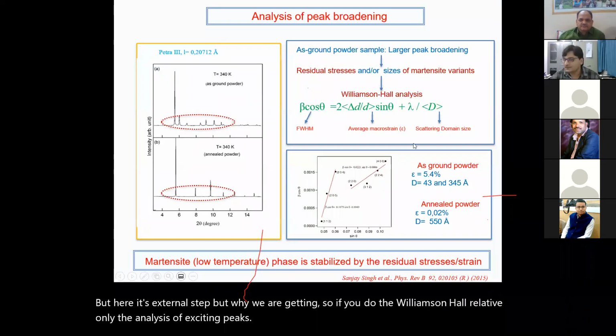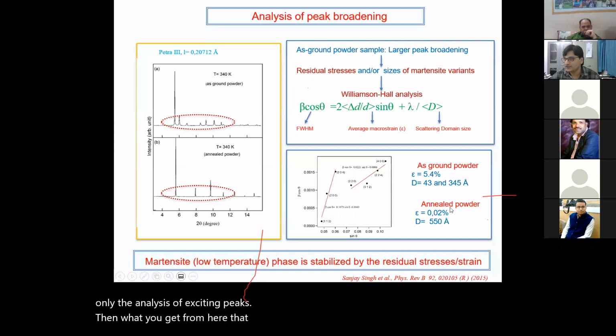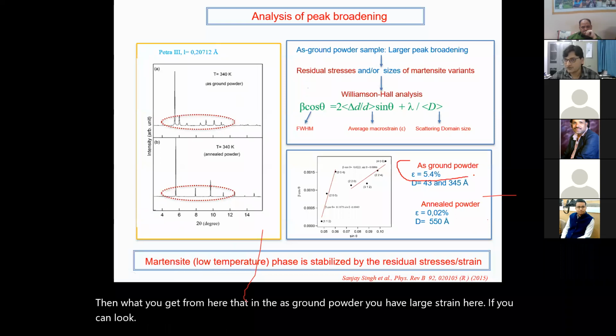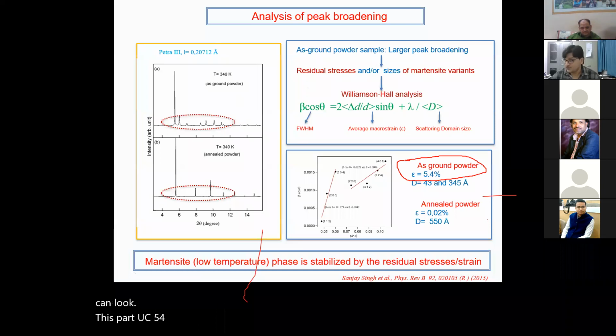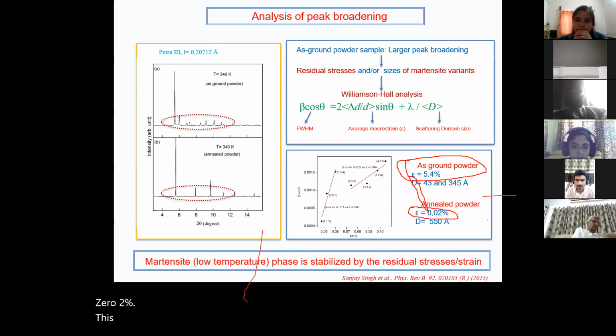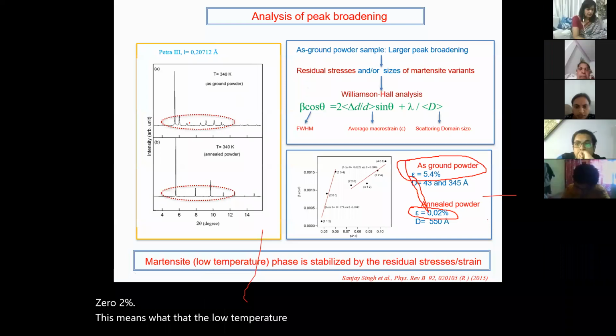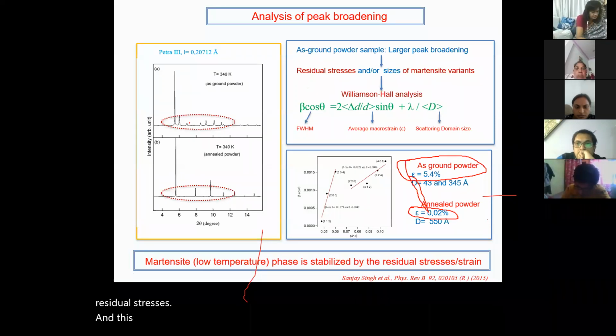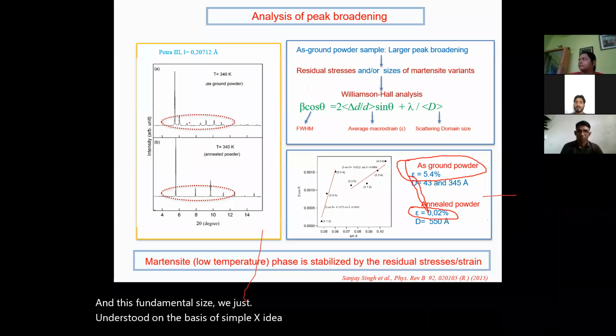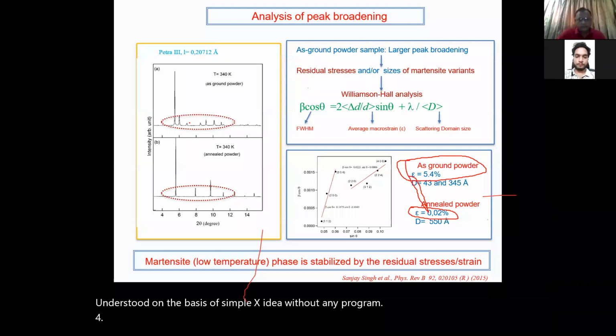Then what do you get from here? That in the as-ground powder, you have large strain. Here, if you look at this part, you see 5.4% strain. And then in the annealed powder, you have 0.02%. This means that the low temperature phase is stabilized at high temperature due to residual stress. This fundamental science we just understood on the basis of simple XRD analysis without any program, Rietveld or LeBail. We can just fit the peak and take the broadening.